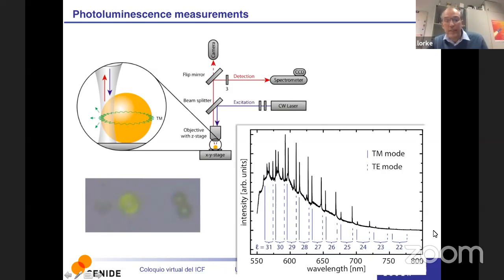And then you can quite precisely determine not just the L, but you also know the wavelength, so you know the circumference of the sphere quite well. You see that for every L, you have two spikes, and that is because one is the TM mode, that's the mode that I'm showing here, and the other is the TE mode, where the electric field would oscillate perpendicularly to what I've shown here as it goes around.